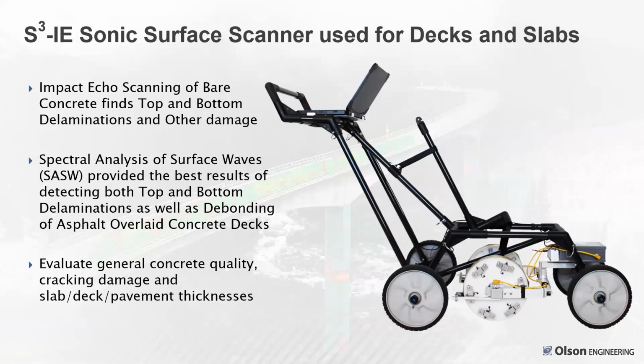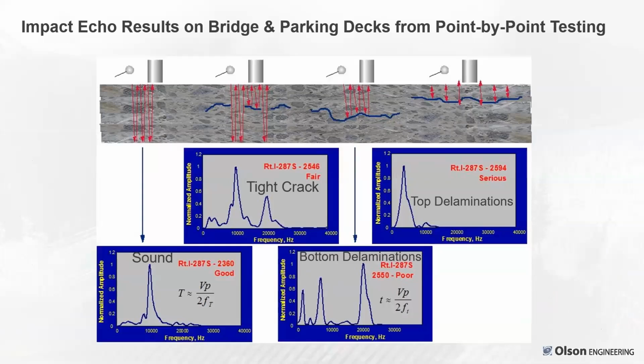So here's the basic scanner. We use it for impact echo scanning of any kind of concrete. We use it on bridge decks. We use it on large slab areas, ramps, parking garages, et cetera. This same unit can also be configured for spectral analysis of surface waves testing, which we've talked about in a previous webinar, for the evaluation of bridge decks specifically. SASW with the S cubed unit works very well for evaluating concrete bridge decks that are underneath asphalt overlays. So we can use this unit for general concrete quality, evaluating cracking damage, top and bottom delaminations, as well as for pavement thickness. And I've got some examples of all of these coming up here.